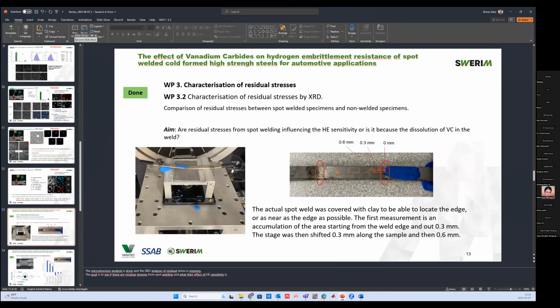Okay, so that was about the TEM characterization. What we can summarize up to now is that we do see carbides in the as-produced material, with a larger number density in V30, but spot welding strongly affects the carbides. In the weld zone we dissolve them in the V15 material, while in V30 we could still see some larger particles and fewer vanadium carbides, while in the heat affected zones they are still present in larger number. Let's have a look at preliminary results for the characterization of the residual stress now.